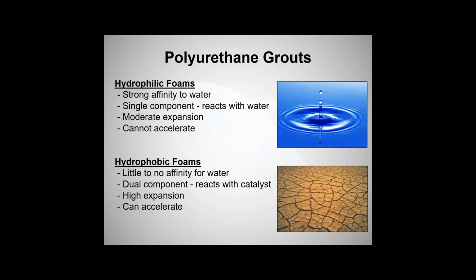So now jumping into the chemical grouts, talking about the solution grouts. Solution grouts is a general industry term. Polyurethane grouts, again, come in two families, hydrophilic and hydrophobic. We've got a strong affinity for water within the hydrophilic family, like "fill with water." That's kind of how I separate that analogy. They're typically single component. They react with the water. When they come in contact with water, that begins a reaction. They tend to have moderate expansion, and they're difficult to accelerate. Sometimes you can do that through heat. They are temperature sensitive, just like any chemical grout.